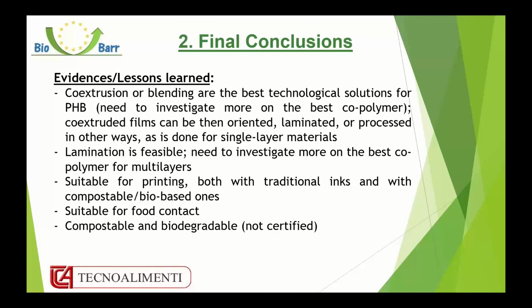Then we have understood that co-extrusion or blending are the best technological solutions for PHB. Obviously, there is still the need to investigate more on the best copolymer. Co-extruded films can then be oriented, laminated, or processed in other ways, as is done for single-layer materials. Lamination is feasible; we need to investigate more on the best copolymer for multi-layers, also in this case.